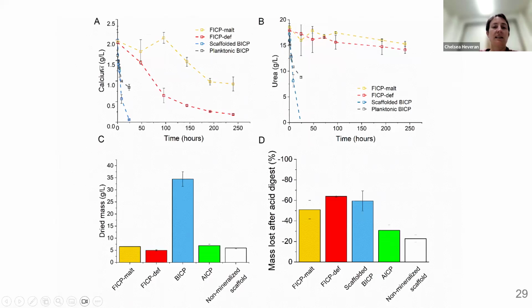So what we can see is that for these BICP conditions, meaning the bacteria conditions, scaffolded and planktonic (planktonic means bacteria by themselves, no scaffolds), in either case, when we have the bacteria, the urea and the calcium are consumed very, very quickly. Nonetheless, we do have urea and calcium consumed, albeit more modestly, by the fungus itself, but it does take its time. We do see a big difference between when we use the defined media versus the malt media.